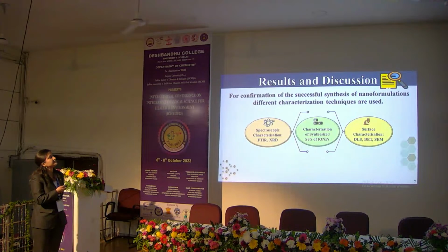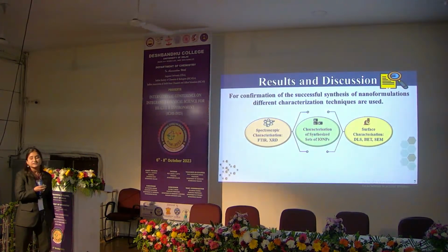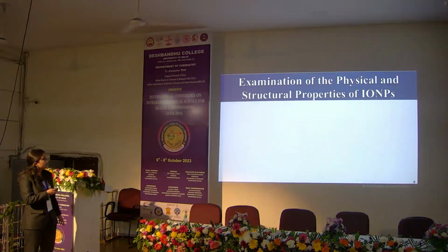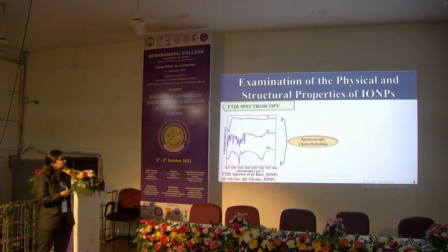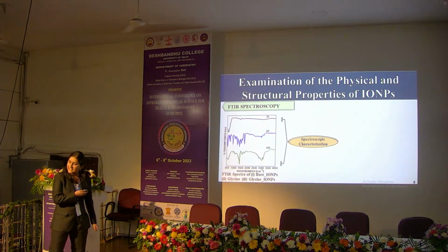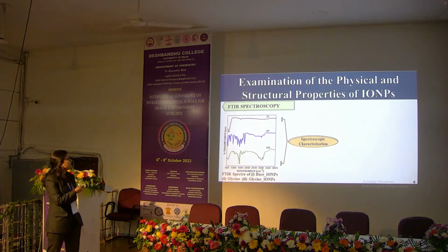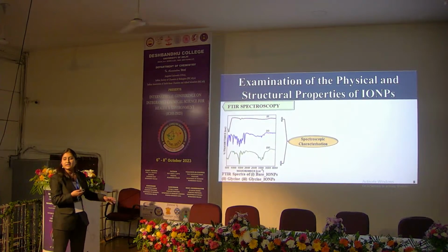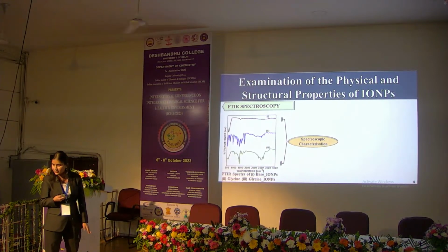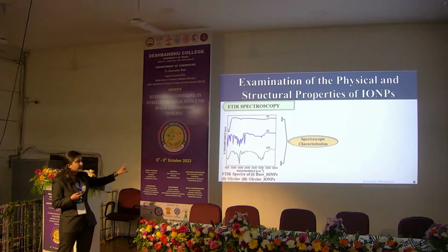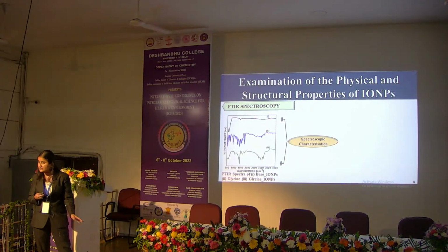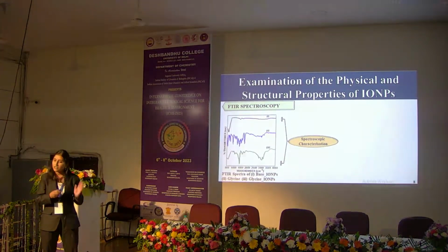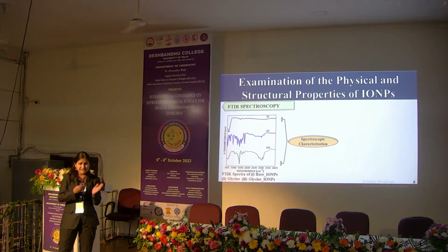Next, for the confirmation of successful synthesis of the nanoformulations, we have done spectroscopic and surface characterization. For examination of the physical and structural properties, we have done FTIR spectroscopy, and from the spectra, as we can see, the peak observed at around 580 cm⁻¹ confirms the successful synthesis of iron oxide nanoparticles. If we compare the spectra of pure amino acid with that of amino acid coated nanoformulations, it was observed that the amino acid coated formulations consist of all the characteristic peaks of pure amino acid with a slight shift in their position.